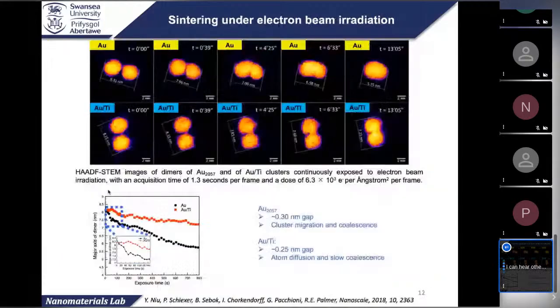And then we use STEM. Basically we just send electrons to the particles. We choose two particles that are close to each other, and call them a dimer. Under the electron beam irradiation, the gold particles come together and become one particle quite quickly, like after 30 minutes here. Then comes the gold titanium. The sintering process is really slow, and it shows a different sintering mechanism compared with the gold.